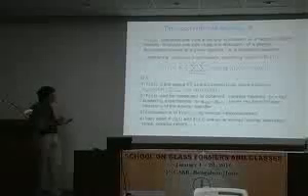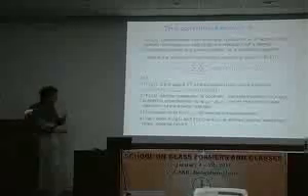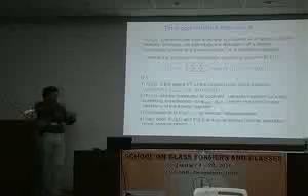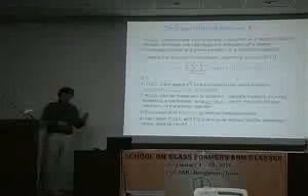If you compare this function with the self one, and we will do this in a second, grosso modo they look similar normally, but there are surprises. Normally the typical relaxation times at a given wave vector of the Fs and the F are quite similar. I'm not talking about a factor of 2 or 3. The height of the plateau is within 10-20% the same. Stretching is quite similar. If you have understood this, very often you have understood also the other quantity, but not always.